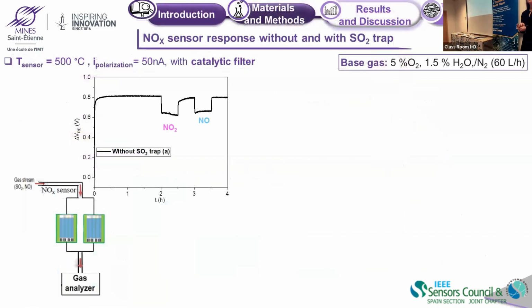So let's go with the NOx sensor response without and with the SO2 trap. Here, the sensor is working at 500 degrees under a polarization of 50 nanoamperes with a catalytic filter. The base gas is composed of 5% oxygen, 1.5% water, and balanced with nitrogen. We can see here the response in black to 100 ppm of NO2 and here to 100 ppm of NO. We see negative responses, which are the responses that we are expecting. This is the classical response for our sensor without trap.